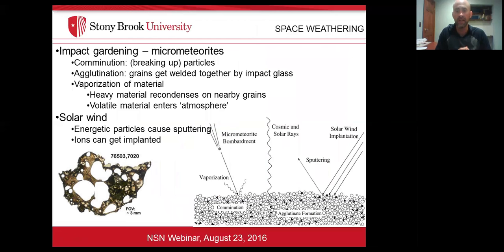Space weathering is a combination of processes, including comminution, which is basically breaking up of particles from micrometeoroid bombardment, vaporization due to impact, interaction of cosmic and solar rays, sputtering of elements, and implantation of the solar wind, which is mostly hydrogen particles or hydrogen atoms. And the result of space weathering are these large, glassy particles that we call agglutinates, where larger particles are welded together by glass. We also see the formation of really iron metal-rich rims on all these grains.